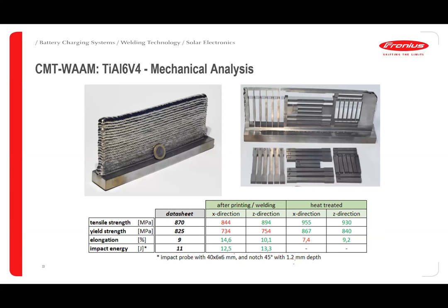You can see the tensile values, where the data sheet value was 870 MPa, we were able to achieve in the X direction 844 as welded, and then in the Z direction, we were able to achieve 894, even better than the tensile strength of the alloy we have used, which is the data sheet value. And you can see the yield strength, which is 825 MPa, we were able to achieve close to around 754 MPa, and the elongation values were also very, very much higher than that of the wire we have used, and the impact energy we found was close to 12.5 and 13.3 vis-a-vis the wire we have used.